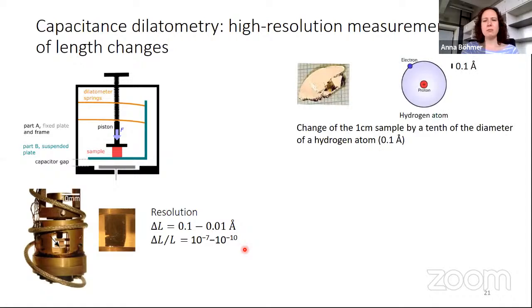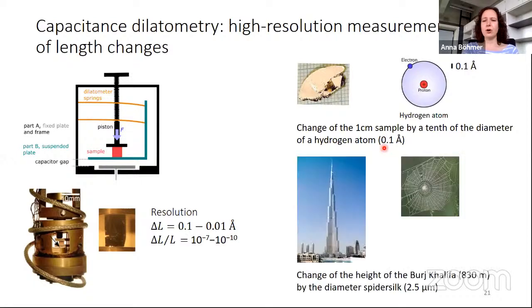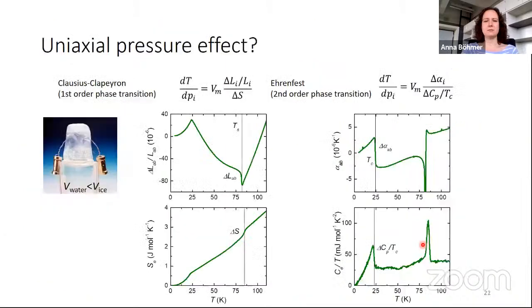Just to find pictures for how much that is: if our 1 centimeter sized sample changes by 1/10 of the diameter of a hydrogen atom, that's 0.1 angstrom. That's a change that can be seen. Or to find macroscopic examples, it's as if the height of the highest building in the world in Dubai changes by the diameter of spider silk. That's a length change that can be seen. And that's something that can tell us about the superconducting properties.